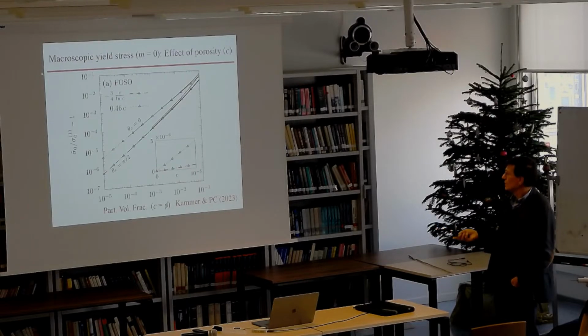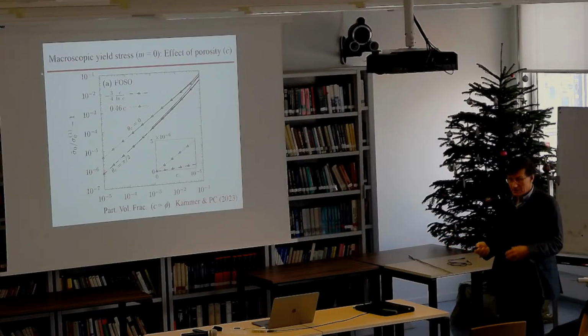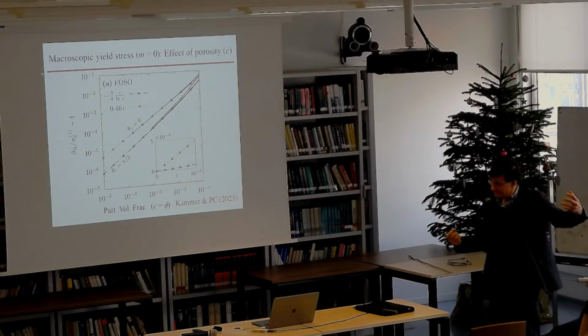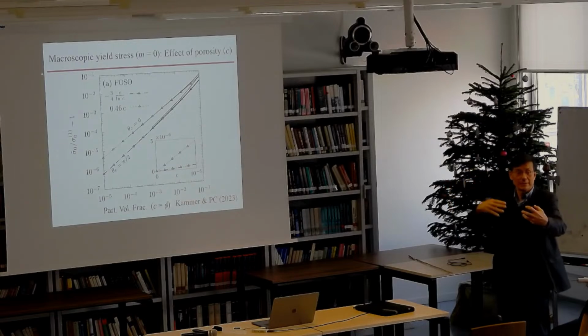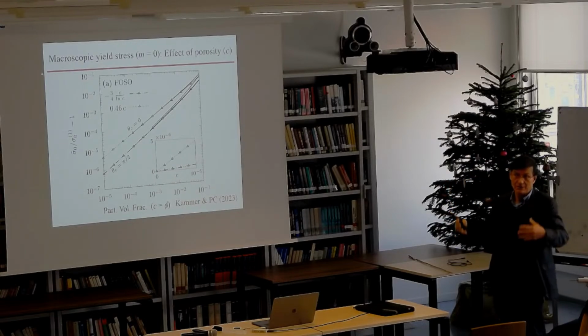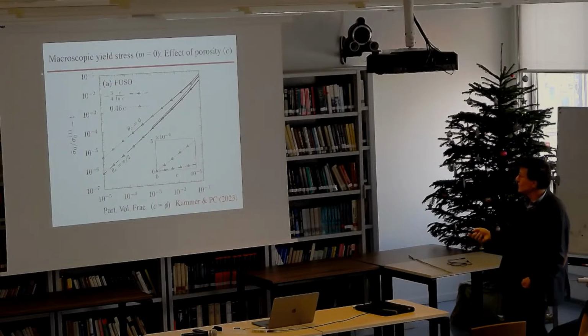And you can go beyond and look at interesting things like the dilute limits. The axisymmetric case, where the fields don't localize, gives a standard behavior that is linear in the volume fraction of the particles. When you look at the shear case, where you have shear bands that tell you the particles are interacting because the bands have to meander around them, there's interaction even with only a few particles.